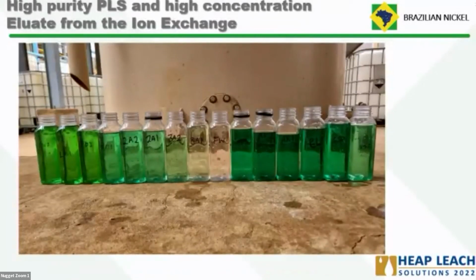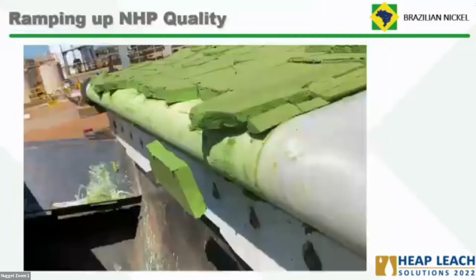This is just a picture that I like to show about the ion exchange application. This is the feed. Right now it's pretty good. It's 12, 14 grams per liter nickel in the PLS. We expect that to go down as the heap matures to maybe 6 or 7. And what the ion exchange does is act as a concentrator. So the eluate, which is the darker green, has 40, 45 grams per liter. So we have a much smaller volume to treat and a much more pure solution that then we turn into a nice green NHP with 47 to 50% nickel right now.